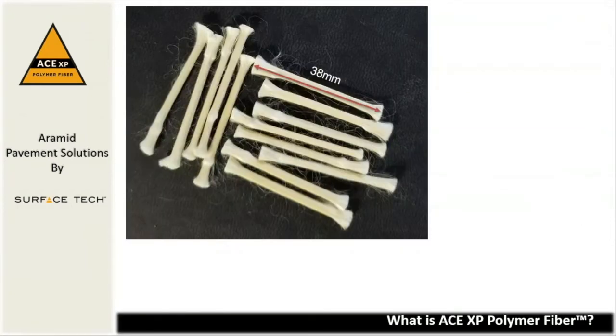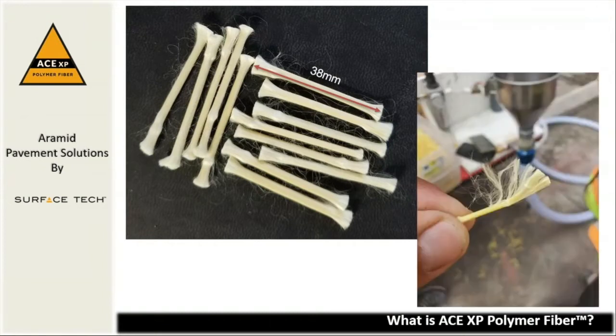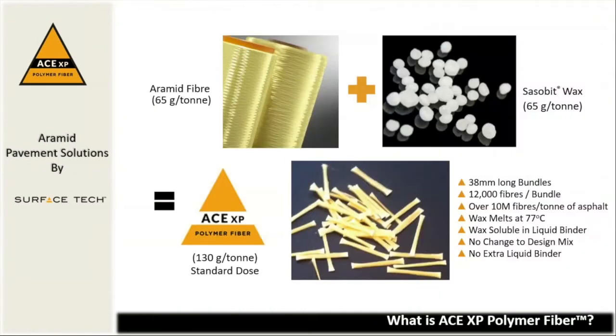Best described as a bundle, each piece of ACE-XP is 38 millimeters long and approximately 2 millimeters in diameter. The bundles can be pulled apart at the ends to reveal the small Aramid fiber, and you can see just how small those really are. ACE-XP is a combination of Aramid polymer and Sasobit wax. 65 grams of Aramid is combined with 65 grams of Sasobit wax, making 130 grams of ACE-XP polymer fiber. We call this a single dose.